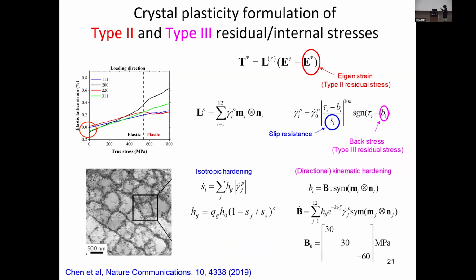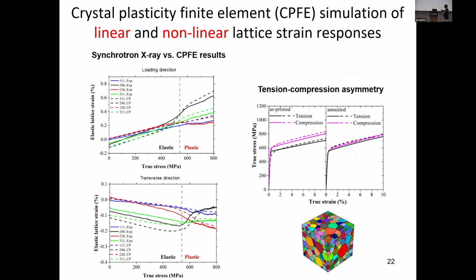So we use the crystal plasticity finite element model to account for those type 2 intergranular internal stresses and type 3 intragranular internal stresses, to quantitatively predict, for example, the lattice strain responses for different grain families. Here you can see the solid lines are the synchrotron X-ray results from APS, and the dashed lines are our crystal plasticity finite element simulations. We can well capture this residual stress effect. Without the loading, the internal stresses are called the residual stress. We can also follow or predict their evolution with the loading, for this behavior response along the loading direction and along the transverse direction. We can also further predict the tension-compression asymmetry.